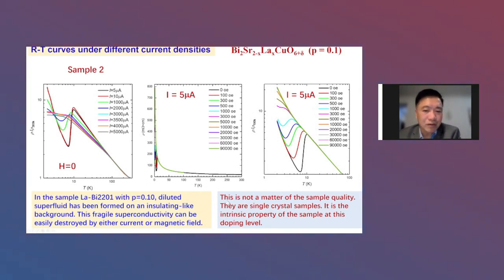So this is not a matter of the sample quality. They are single crystal samples. It is the intrinsic property of the sample at this doping level. It says that we have a fragile superconductivity on top of a strong correlation background, okay, even for this sample at this doping level.